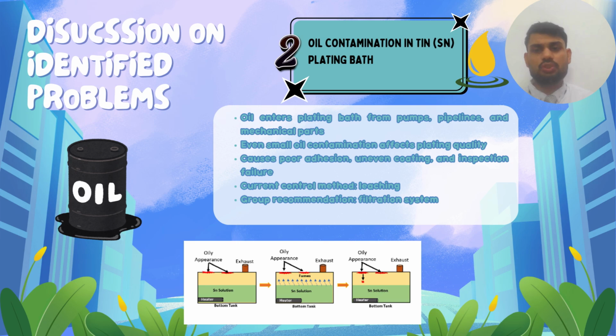Currently, leaching is used to remove oil and restore chemical balance. However, leaching requires downtime and increases operating costs. Therefore, our group recommends installing a filtration system to continuously remove the oil and fine impurities. This helps stabilize the plating bath, extend chemical life, and reduce the defects.